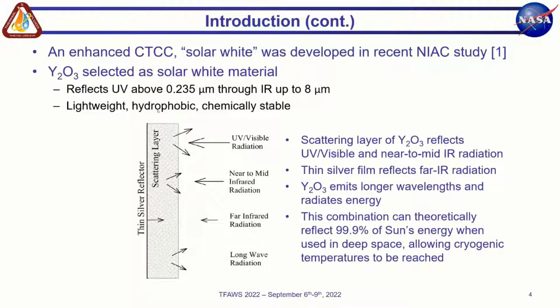So in a recent NIAC study, an enhanced cryogenic thermal control coating called solar white was developed and tested. There were many different materials that they looked into as potential solar white materials. Ultimately, yttrium oxide was selected because of its ability to reflect UV above 0.235 microns through infrared up to 8 microns, so that basically covers the entire wavelength band that you saw in the previous plot. Yttrium oxide also is lightweight, hydrophobic, and chemically stable, which is exactly what we're looking for in this kind of application.